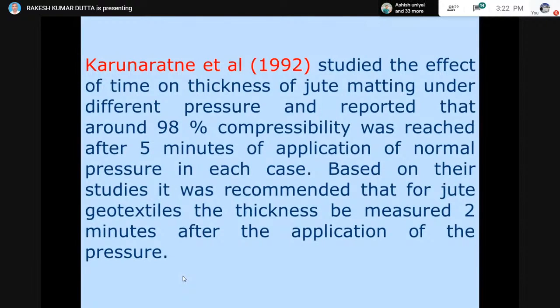So this was the main conclusion drawn from one of the studies reported by Karunaratne in 1992. Based on this study, it was recommended that the thickness of jute geotextile can be measured 2 minutes after the application of the pressure. So if you want to measure the thickness of natural geotextiles, in case of jute, you can measure its thickness after the application of some normal pressure for a period of 2 minutes.